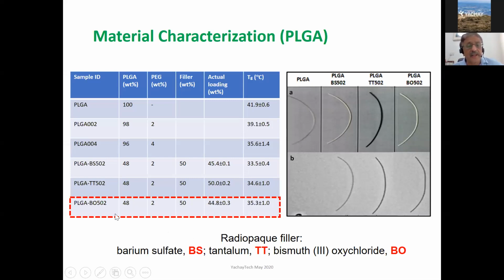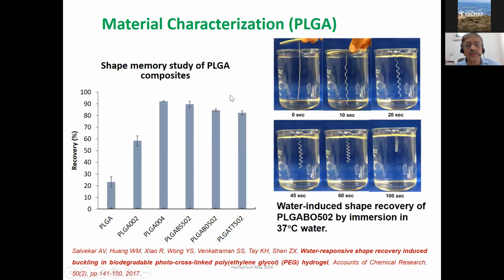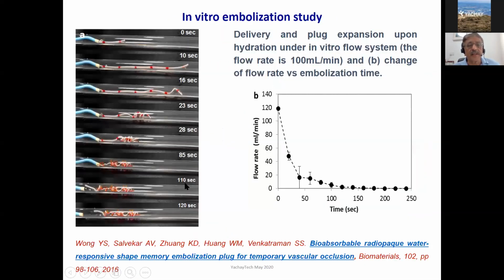Bismuth oxychloride nanofiller inside a PLGA system, and the filler content is about 50%. And we did a number of shape memory studies and recovery studies, which I will not go into, and then developed an in vitro evaluation of the time it takes to completely block the vessel. And then we went on to an in vivo study inside a porcine pig model. And I will show briefly what happens in a rabbit model.